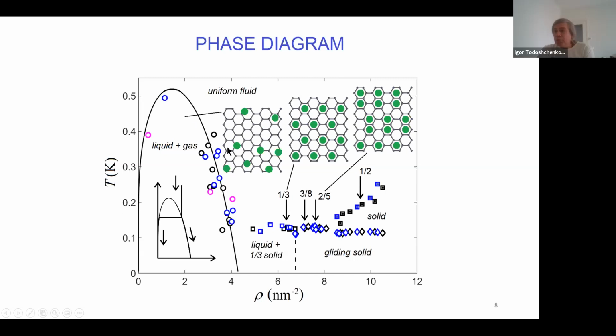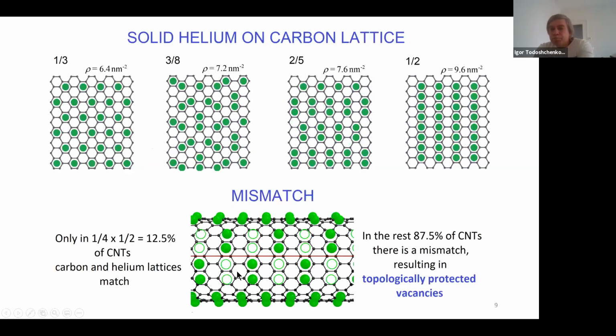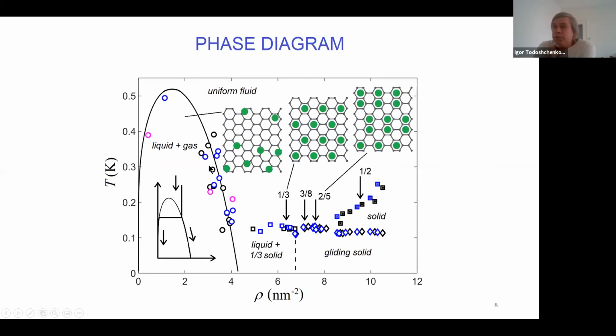So this is the lowest density where we have liquid plus gas coexistence, which transforms to the uniform fluid above the critical temperature. This is a fit with the van der Waals equation, this line here, and it fits quite well, I would say. Here I illustrate this phase, so that there is a liquid cluster and a rarefied gas.